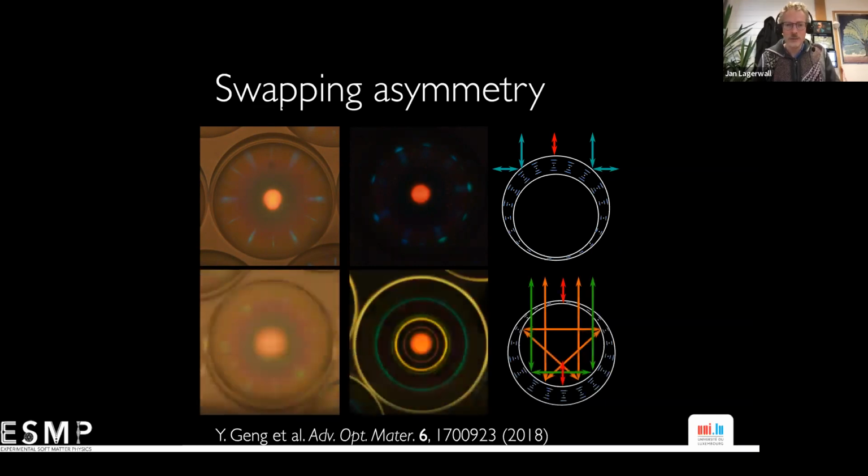But if you turn the shell around, so the thinnest part is at the top, then it is so thin that light enters the shell, because you need a certain number of pitches to get all the light reflected. So if it's too thin, it goes through a little bit, but then it hits the thick side on the inside. And there you can have many different types of reflections that eventually kick out the light on the other side. And this type of internal reflection gives you an optical echo chamber, if you like.